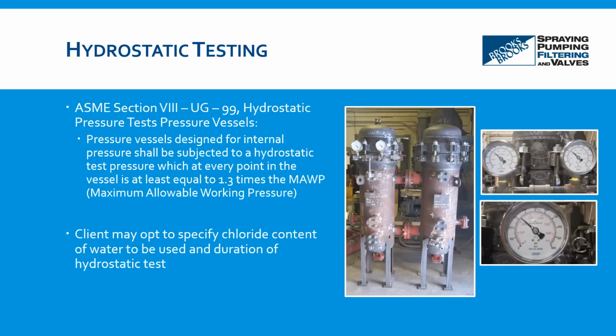And the client could also specify a specific duration of the hydrostatic test. Minimum, we would typically test for 30 minutes. And this is an inspection point for any U-stamped vessels. So the technical authority would have to be present during the hydrostatic test.